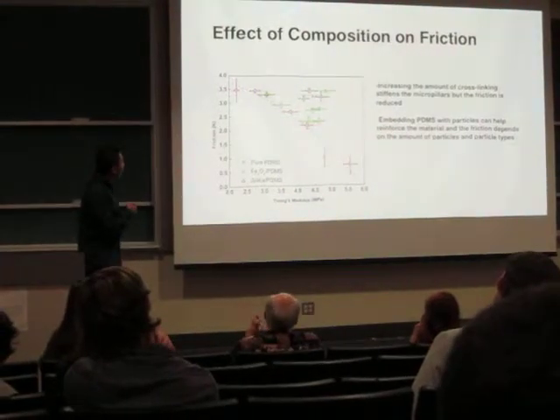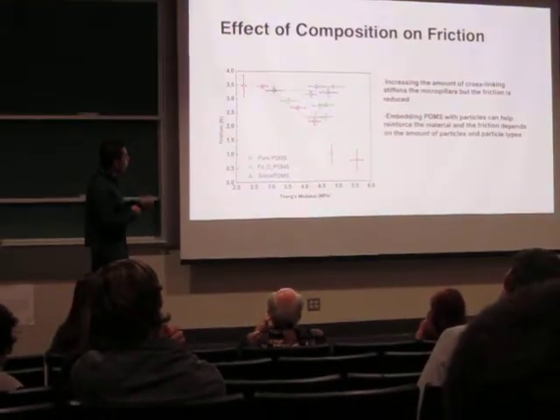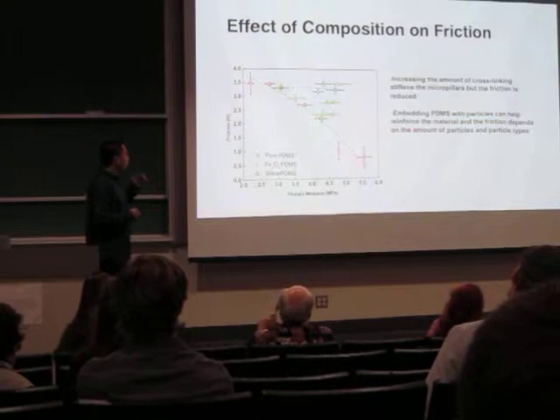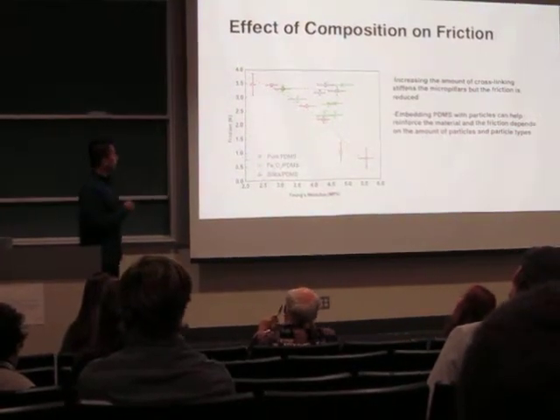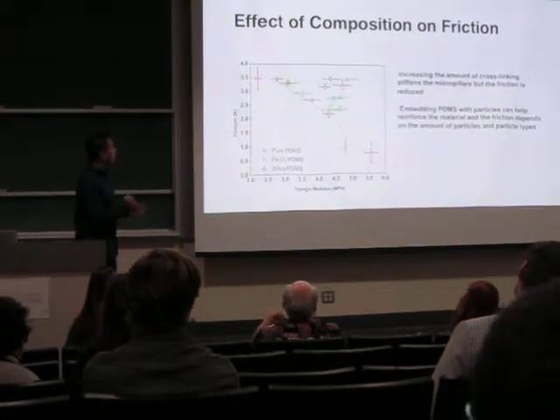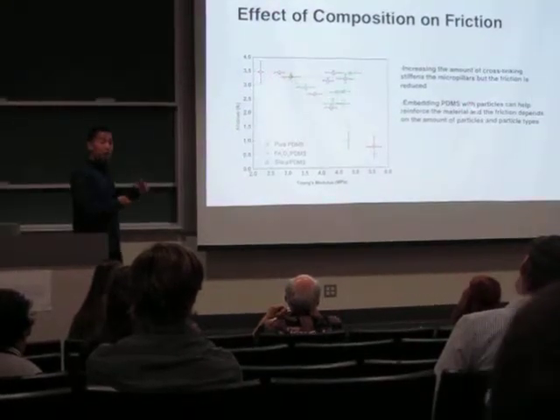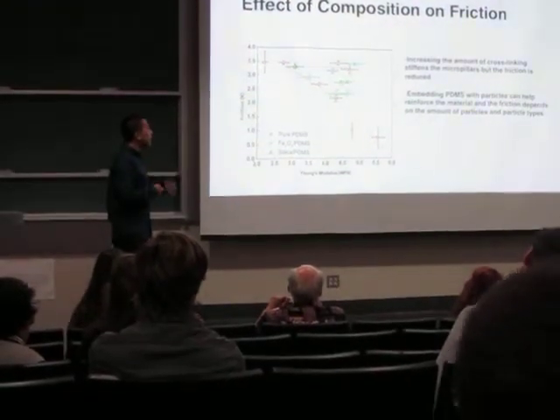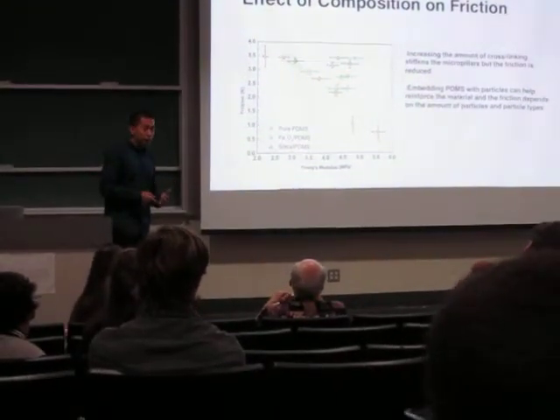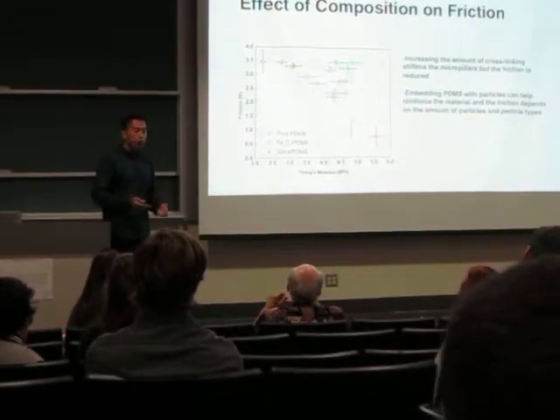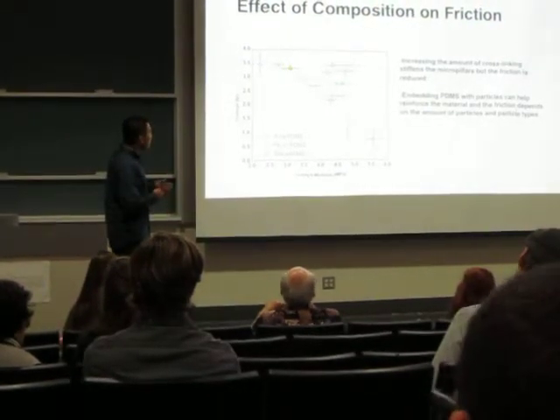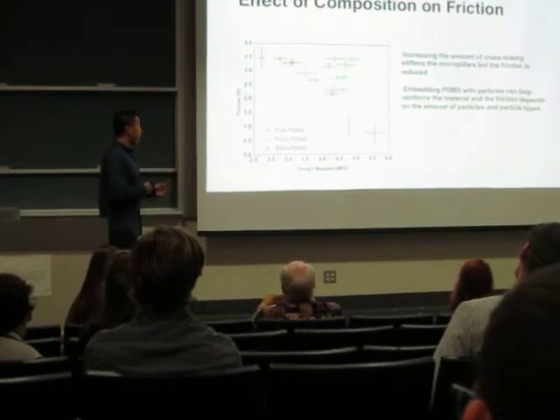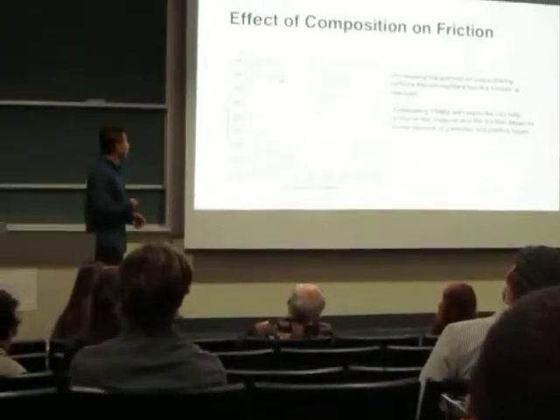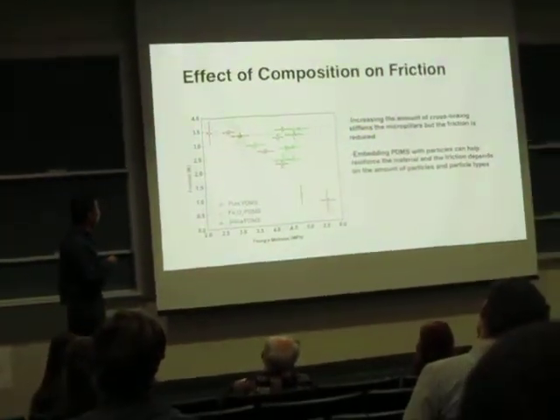So we see that as we add more curing agent, the Young's modulus increases from left to right, but the frictional force actually dropped. So we can increase the strength of the material, but we reduce the frictional force. And then we have the second scenario, where we add black iron oxide particles, which is the green one.